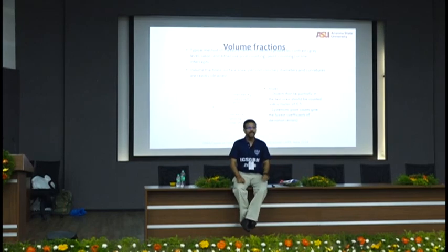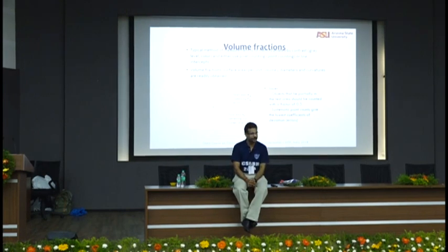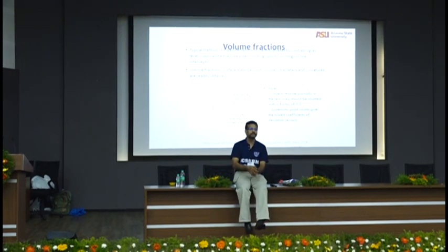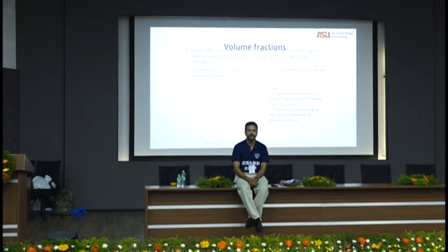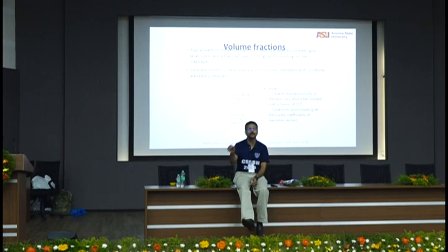Finally, what I'll do is, I've counted 1000 points, and if 200 of them are pores, I'll say my porosity is 20%. And if I had 1000 points and 500 of those points were in the paste, I'll say my paste is 50%. And if I had 300 aggregates, I'll say my aggregate is 30%. So use that as a point counting method.